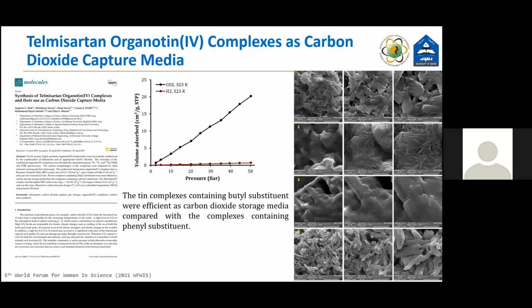The next one, the Telmisartan organotin complexes as carbon dioxide capture media. The FESEM image of the synthesized organotin complexes revealed that the complex have a homogeneous and porous structure. In addition, this image shows the presence of tiny particle agglomerates, and organotin complexes have different shape and particle size. These complexes contain a butyl substituent were more efficient as carbon dioxide storage media than the complexes contain a phenyl substituent. The dibutyl complex had the highest BET surface area and the largest pore volume, and the most efficient for carbon dioxide.